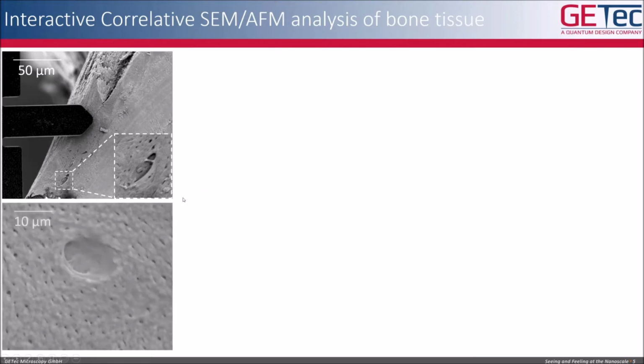Using the SEM, it is quite easy to find these lacuna spots on the surface of the bone structure, and then you can maneuver the cantilever directly to the position of interest on top of this lacuna and take an AFM image of exactly this lacuna area that you see here.